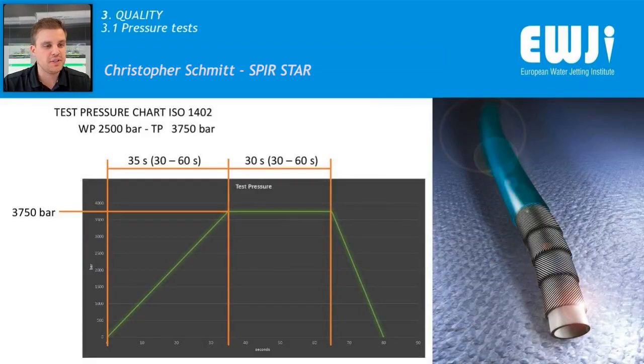This graph shows a typical pressure curve of the ISO 1402. So you see also that the working pressure of this sample of the hose was 2500 bar. This results in 3750 bar with a test pressure factor of 1.5. So this test pressure of 3750 bar should be reached within 30 to 60 seconds and should be held for a period of time of 30 to 60 seconds. And during this holding time, there should be no unusual pressure drop or any signs of leakage.